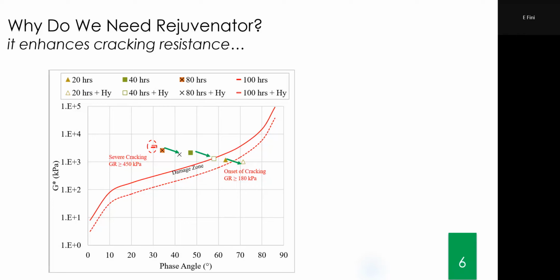So the 100-hour aged material at that point was just too aged for any meaningful restoration. The other three did change, so there is some hope for them to get improved. But you can see the one after 100 hours did not even move. So that's one indicator of restoration.